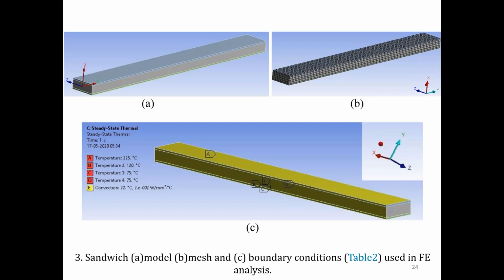But here, in the conventional manufacturing method, the prominent failure phenomenon which occurs is debonding between the skin and the core. And this was the major disadvantage of these conventionally manufactured sandwiches. So we thought, let us completely eliminate that by printing a sandwich at one go, all at once, so that we will not have any delamination between the skin and core, and that we did achieve. Especially when we want to print a sandwich with complex geometry, conventional manufacturing methods poorly exhibit the properties, but in 3D printing, as it has design flexibility, we can exploit it for quick realization of these complex geometry sandwiches, and that too without any delamination between the skin and the core. So that's the philosophy behind printing the sandwiches here.